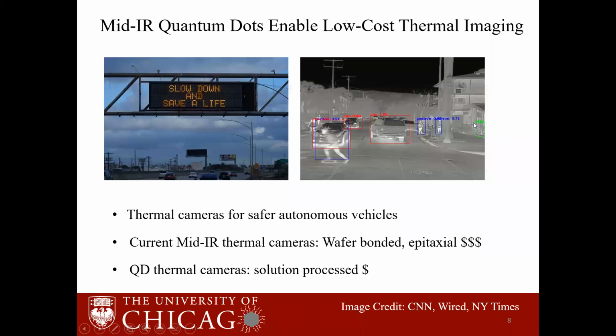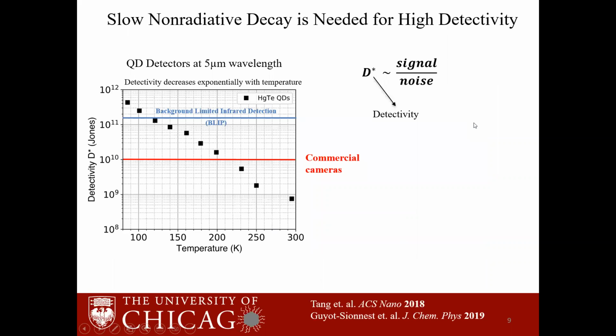The biggest bottleneck for bringing the quantum dots to commercialization is that they need to be cooled to very low temperatures for getting a good sensitivity. So on this graph, we have the detectivity D star for mercury telluride quantum dots as a function of temperature. And mercury telluride is the most common quantum dot material used for thermal imaging. The detectivity is a measure of the signal to noise ratio for the camera, and this tells us how sensitive the camera is. For quantum dot thermal cameras to be comparable to commercial cameras, the detectivity should be around 10 to the 10, which is this horizontal red line.